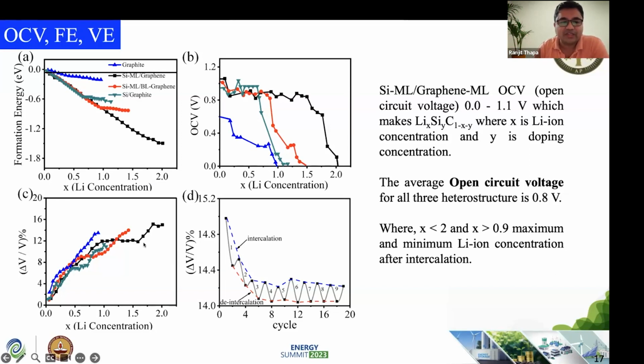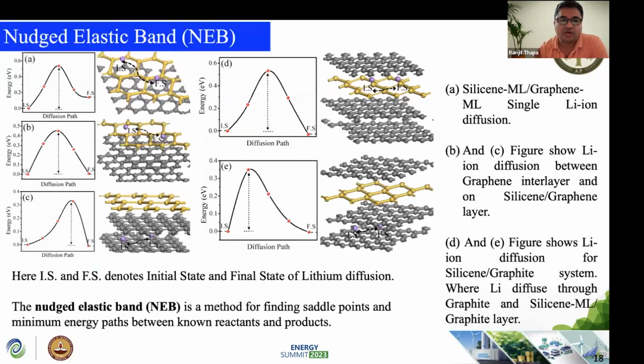So, and the volume expansion looks very good even if we put the silicon. And the main thing is that it is not about the putting of the electron, it is also a removing of the electron. So what will happen when you are putting the cycle? Is it really form a stable and other things? And we found that yes, the structure is stable even after 20 cycles. So this is the first time we have shown that theoretically also we can show the cyclic process of the lithium intercalation and de-intercalation. So after that, what will be your diffusion?